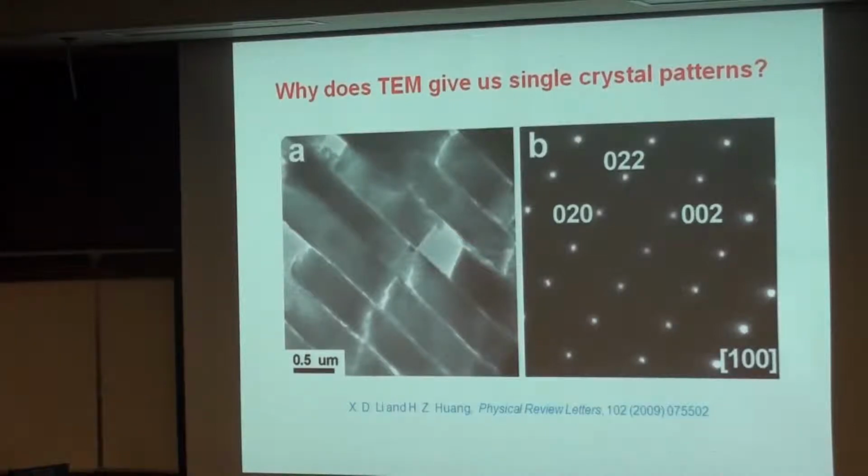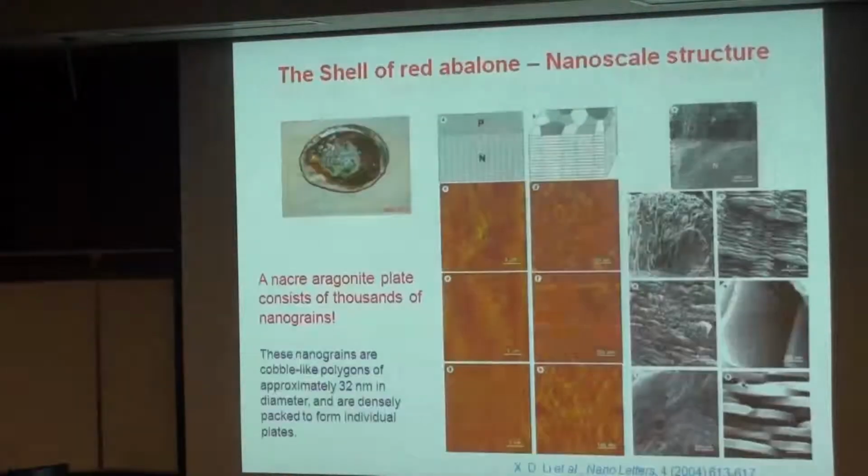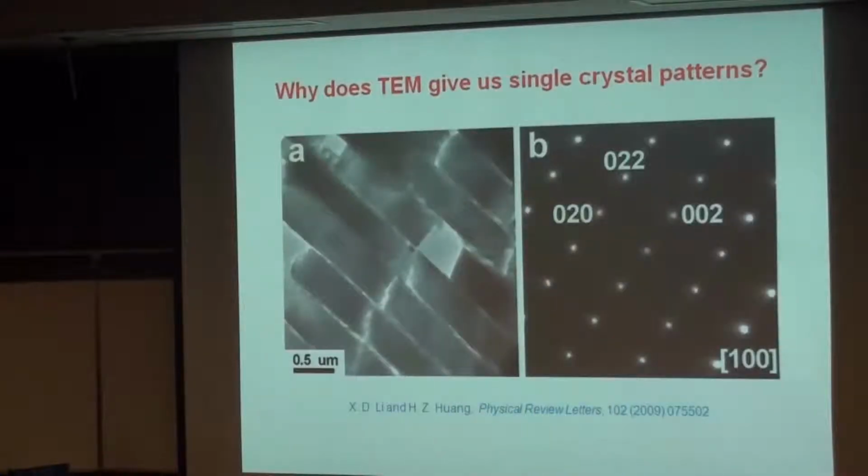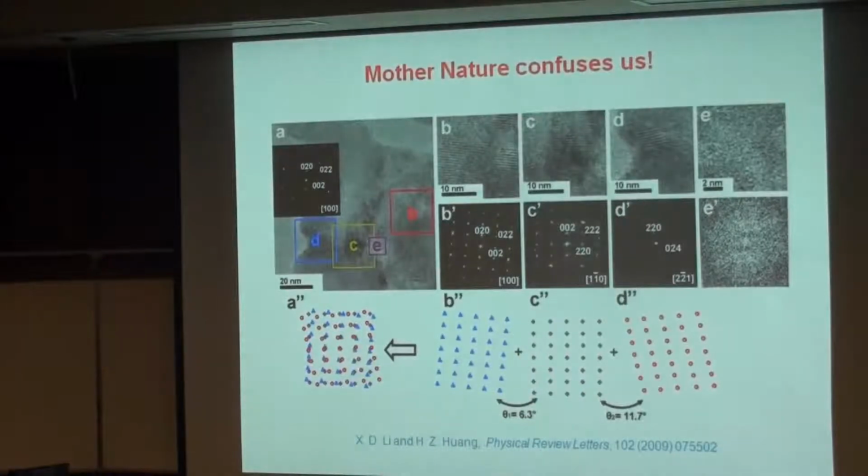But why did you see previously in this paper, using the AFM tapping mode, tons of nanoparticles? But from the TEM, you can see those bricks, they are single crystal. This is a single crystal diffraction pattern. Okay, very lucky. University of South Carolina, my previous university, bought the HRTEM, and we look at this brick, and if you select the entire area, you can see this diffraction pattern is single crystal. Okay, a recognized single crystal, 100.